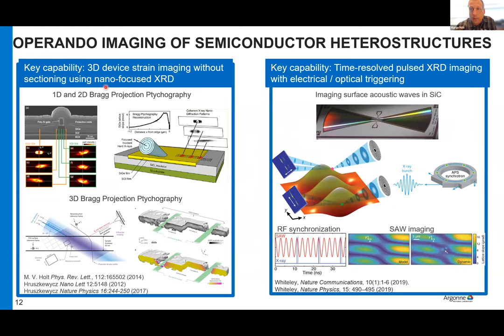Okay, so how do we do this? There are two main capabilities to keep track of. One of which is Bragg projection ptychography, originally developed by Stefan's group at Materials Science Division, that lets us look within these fabricated heterostructures and interpret the far field scattering patterns as both strain and curvature gradients, in one dimension, two dimensions, and actually utilizing the detector viewpoint of the illuminated coherent volume, you can do this in three dimensions. That was a key development that Stefan got to a few years back, where you're able to use the scanning dimension in an analog of light sheet fluorescence microscopy to create a three-dimensional image of three-dimensional strain without rotating the sample at all. And of course, by synchronizing this time source, you can look at dynamic processes.